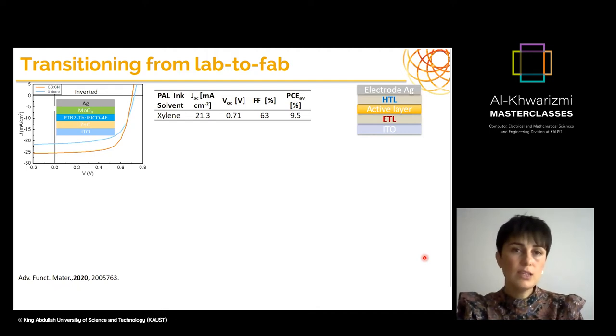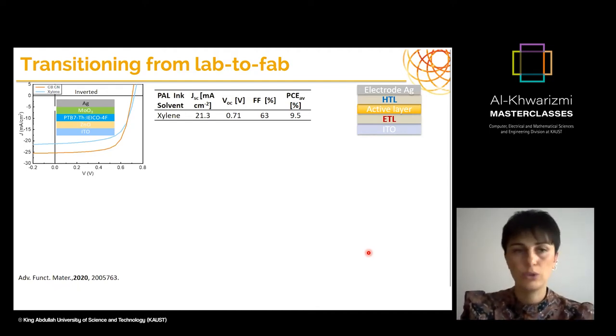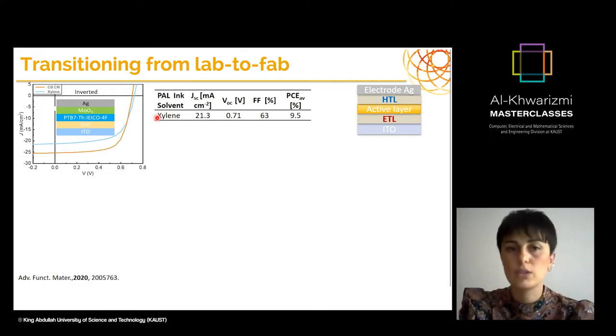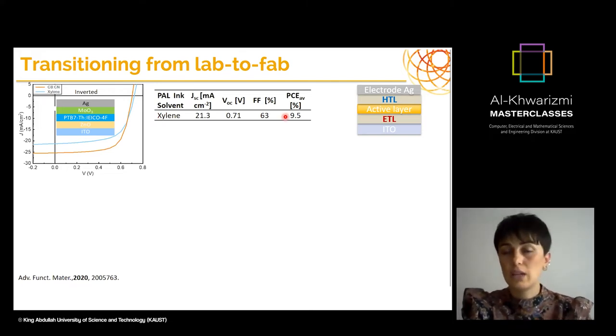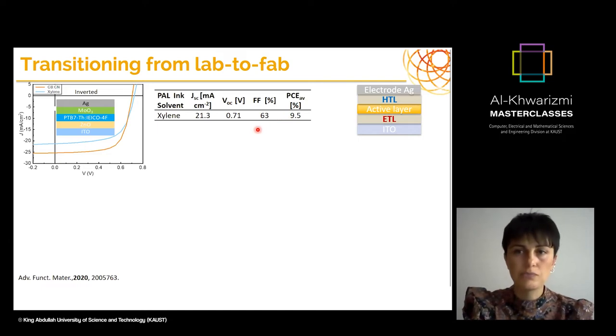So then we moved into potentially high performance materials, as I showed you in the first slide of the organic photovoltaics. And this is another photoactive layer, PTB7-Th as donor polymer, and IEICO-4F as an acceptor material. And in this case, as you see, we moved away from these chlorinated solvents, and we optimized this printing with an environmentally friendlier solvent called xylene, and achieved around 9.5% efficiency.